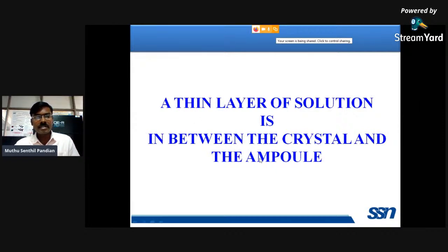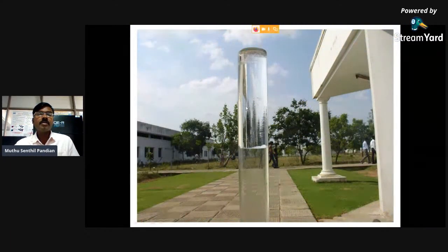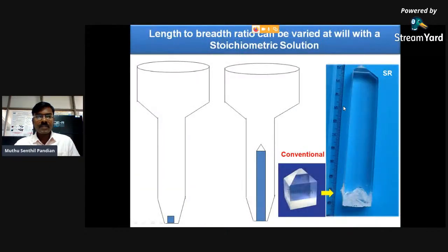And a thin layer of solution is in between the crystal and the glass ampoule. So there is no mechanical stress in the grown crystal. The length to breadth ratio can be varied with a stoichiometric solution, depending upon the pH of the solution. So the growth direction can be maximized in any crystal.